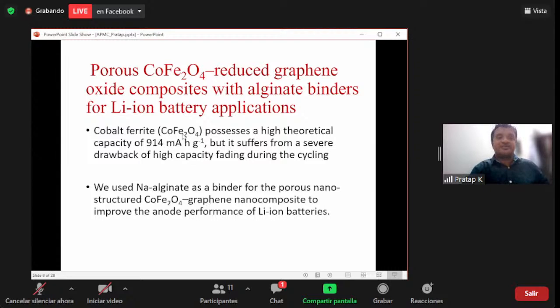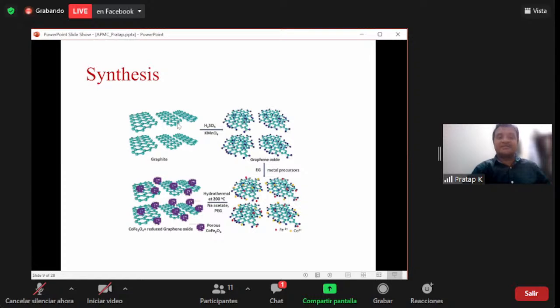Now, this is cobalt ferrite. Cobalt ferrite possesses a high theoretical capacity, 914 mAh per gram, but it suffers from capacity fading. So when we say it is suffering from capacity fading, we thought we could add a binder into it. So we added a sodium alginate binder into this porous structure, and we want to enhance the performance of lithium-ion batteries. So this is the synthesis method.